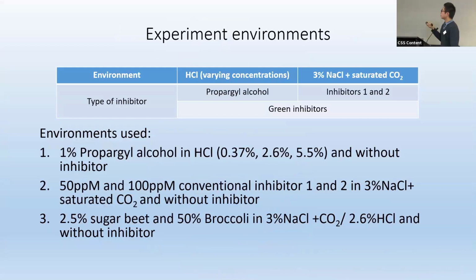Here is the environment for the testing. I used 1% propargyl alcohol in 3 different concentrations of HCl solution and compared with no inhibitor. I used 2 concentrations of inhibitor, 1 and 2, because of a confidential agreement, so I just refer to them as inhibitor 1 and 2, in 3% sodium chloride and saturated CO2 environment, and compared with no inhibitor. And I have used 2.5% sugar beet and 50% broccoli in those 2 environments, compared with no inhibitor.